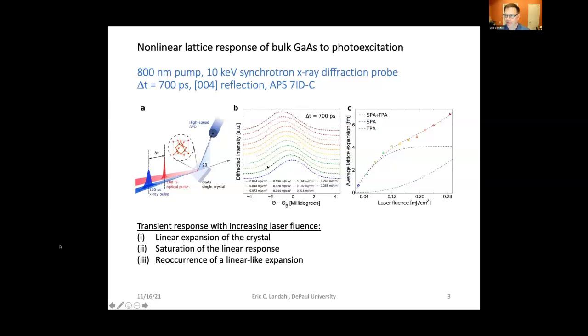So as we increase the intensity and rock the crystal back and forth, we make these very fine rocking curves, which in this case shift to lower angles, implying, of course, a lattice expansion of the material. And then we plot out simply the centroid shift, giving us the average lattice expansion in femtometers via Bragg's law. And there's our curve that looks like the elastic band. You see at first, at these lower bluer colors corresponding to 0.02 millijoules per square centimeter, fairly linear behavior. It then saturates, and at that point starts growing again.